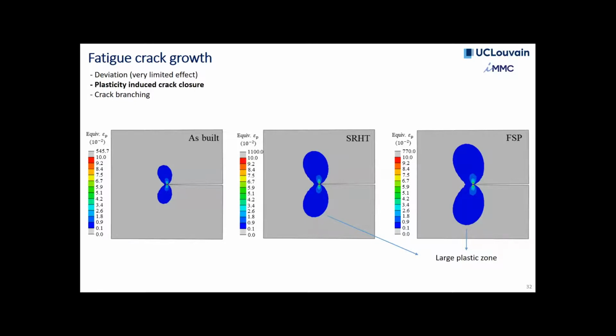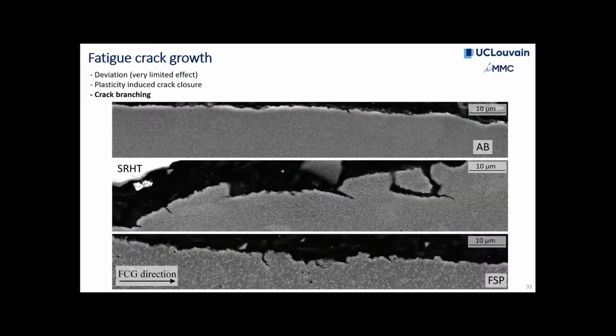We thought there must be another explanation for these properties. We simulated the plastic zone in front of the crack tip, and one thing that we can definitely think of, due to the lower yield strength of the material, is that the plastic zone is larger in front of the crack tip for the stress relief heat treated material and the FSP material, and these are favoring plasticity induced crack closure, so closure of the crack while you're propagating the crack, and this really slows down the crack, causing some compressive stresses in front of the crack tip. So this could be one of the explanations. What we think is one of the most interesting effects is this crack branching.